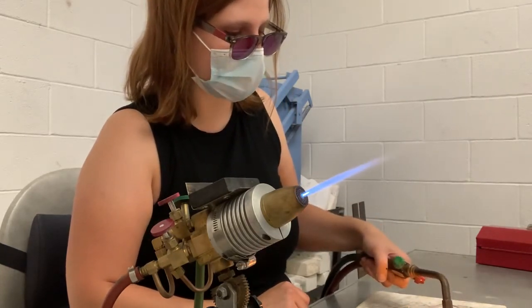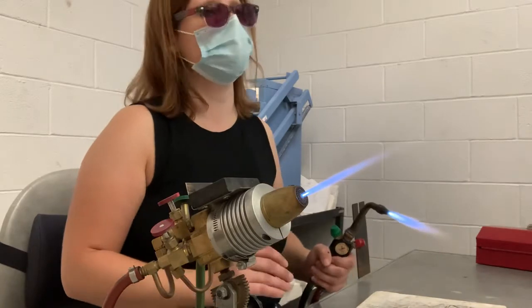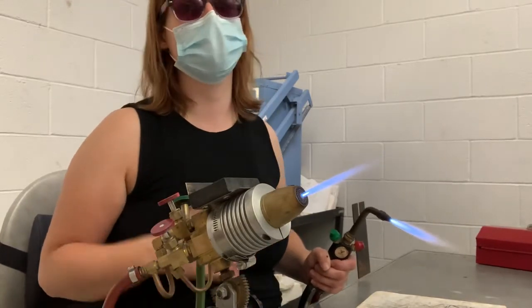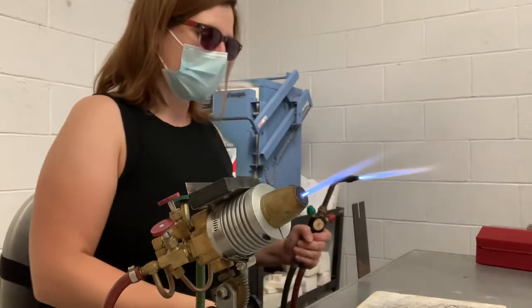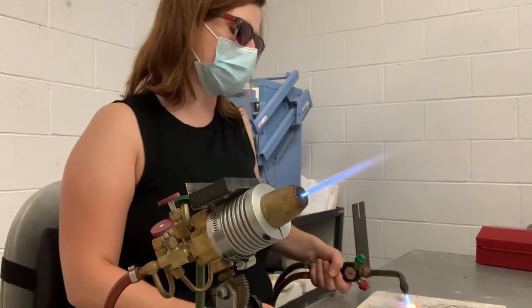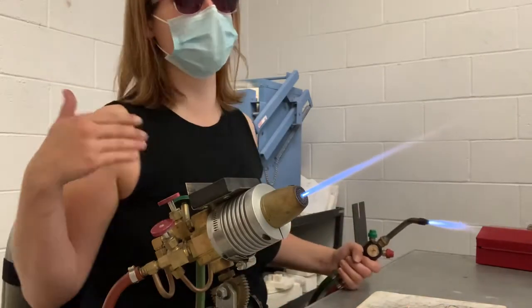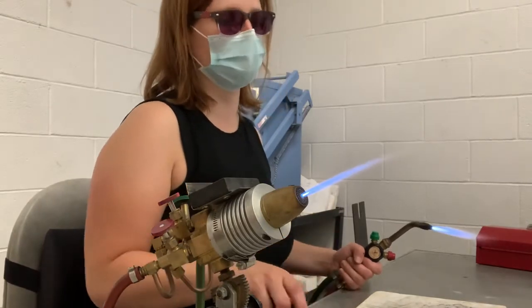When I'm heating on the kiln shelf, it's important to note that if you heat the kiln shelf too much your glass will fuse to it. You can sometimes get it off, but it'll have a texture of kiln shelf on it. It can even stick permanently — that's a real bummer. So rather than heating straight down, I'm going to heat at an angle from the side, which lets me heat the glass more and the kiln shelf less. If the kiln shelf is glowing a lot, it's getting too hot — just move to a cooler area.